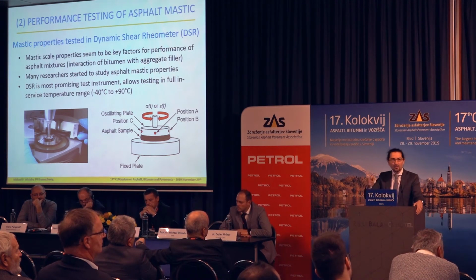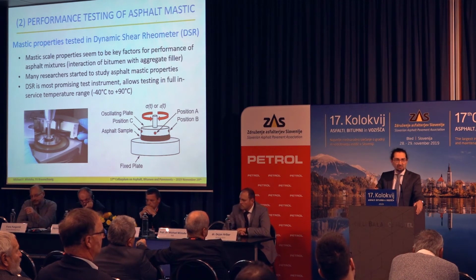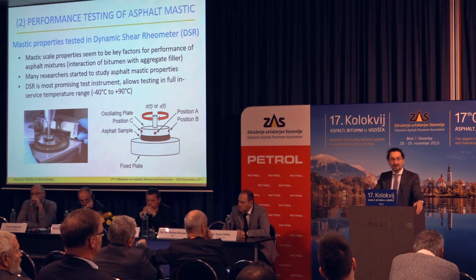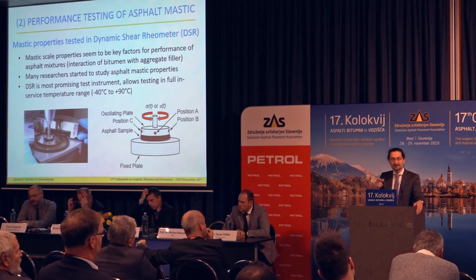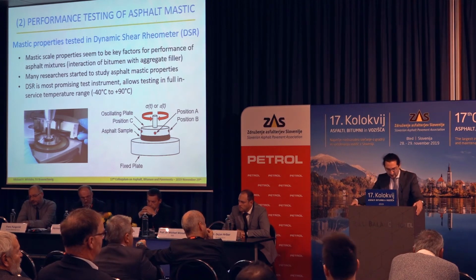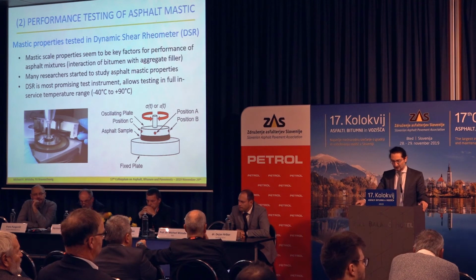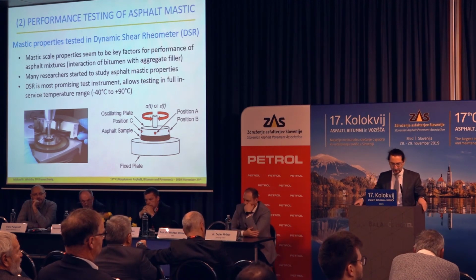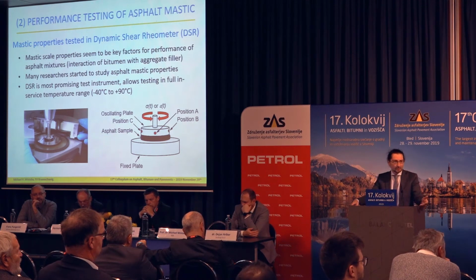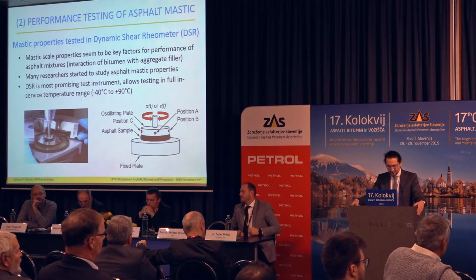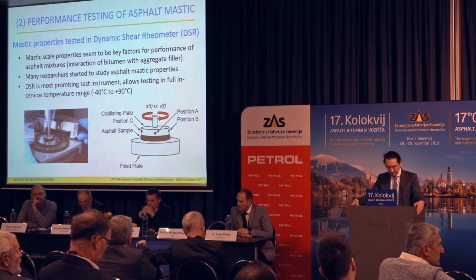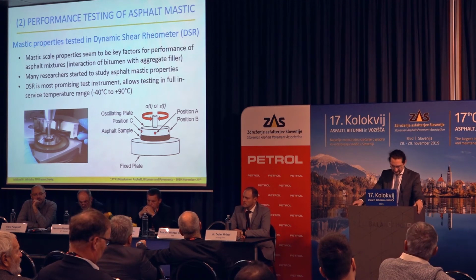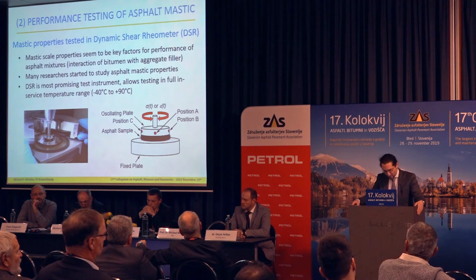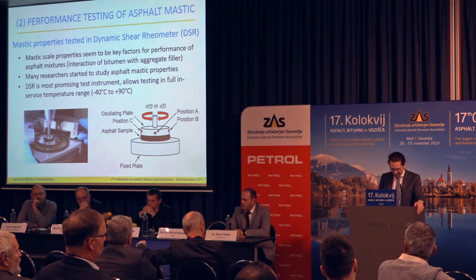And you can combine, let's say, a bitumen of poor performance properties with the right filler, and you will get very nice performance properties, and the other way around as well. So it's good to consider this interaction of bitumen with filler. So a lot of researchers started to study asphalt mastic properties, and most of them use the DSR. There are different equipments you can use, and the most promising technique, I would say, is the oscillating mode within the DSR, which you can see here on the figure.